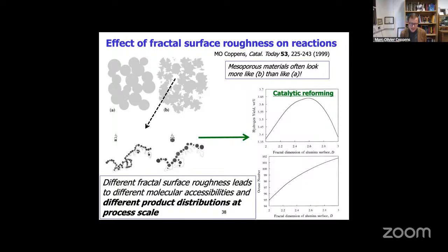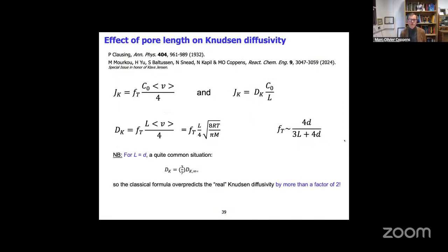And what I'm really excited about is that now we can control these pore roughness. So something as a side note that I want to mention to you is also that pore length has an important effect on Knudsen diffusivity. This seems to be often forgotten, even though this goes back to work of Clausing in 1932 and even Dushman in the 1920s. Right? There's a certain transmission probability, FT, of going from one side of a channel to another side. And this was tested in their case with vacuum experiments and with theory.